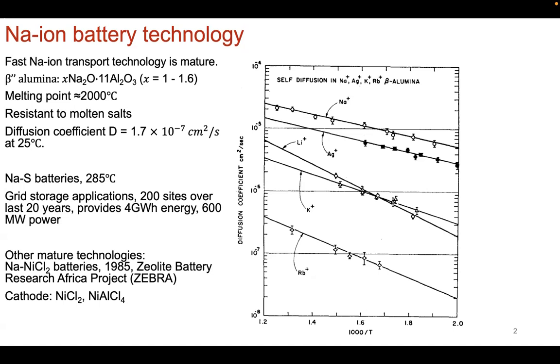This material is a fantastic solid ion conductor. Okay, if you look here in terms of chemical stability, the diffusion coefficient is extremely high, right? It's 1.7 times 10 to the minus 7 centimeters squared per second, and that's at room temperature. And that is like orders of magnitude more than any of the lithium-ion diffusivities that we've talked about before. It's also a really attractive material. It has a high melting point, stable up to 2000 C. It's resistant to molten salt, so now you can run molten salt batteries at higher temperature.